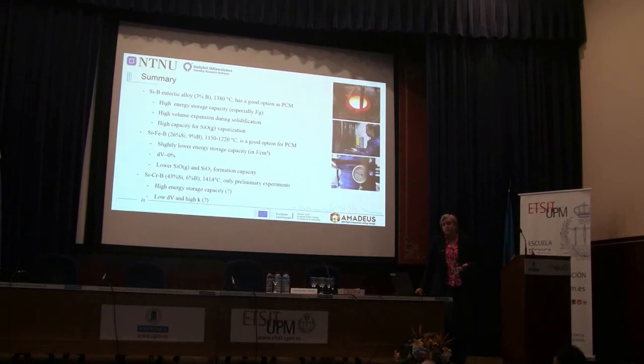I have actually done some experiments with silicon-iron only as well. So it is a possible material, with maybe a slightly lower enthalpy change. However, we also see that the boron seems to suppress some of the oxidation of the alloy, even with 3%. So I think that is an optimization procedure we have to do based on cost and the effects of the different elements. Because boron will also affect the volume, but you could use other, cheap materials for that. Right. So I think it must be a final evaluation afterwards. Thank you.